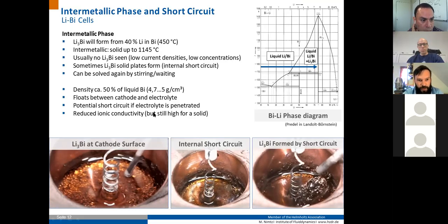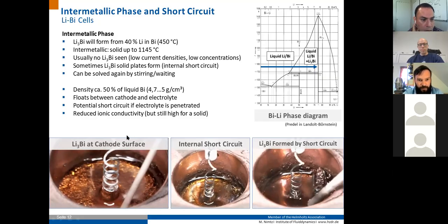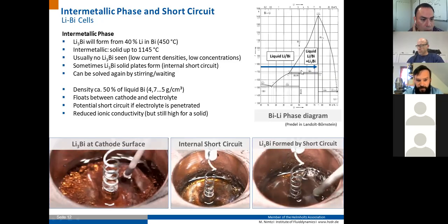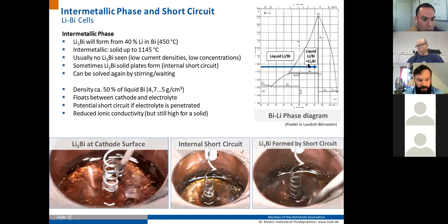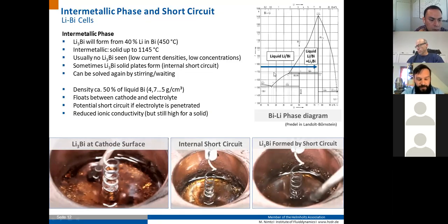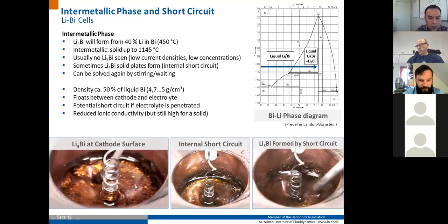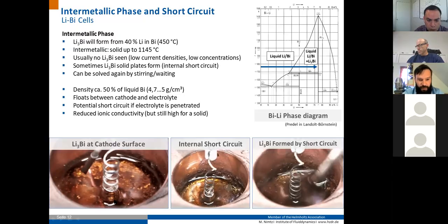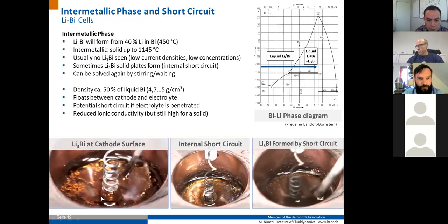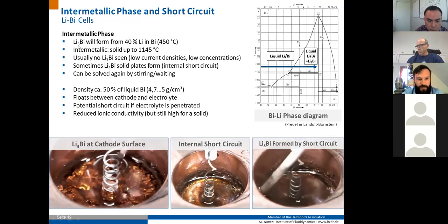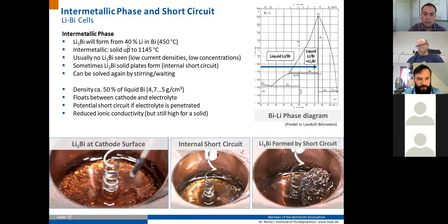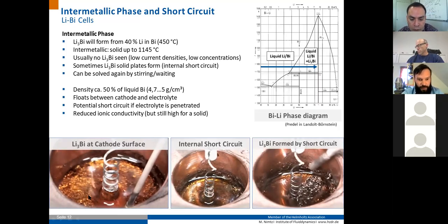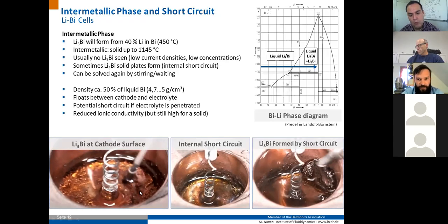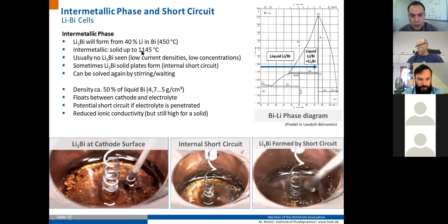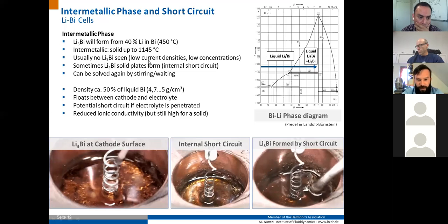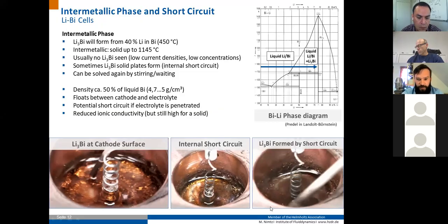This is something you usually try to avoid because the intermetallic phase, the two-phase region here, has a lower diffusion rate for lithium, which means the discharge behavior will not be as good as fully liquid metals. Typically, for a lithium bismuth cell, the intermetallic phase will form at 450 degrees Celsius from 40% lithium in the alloyed electrode. And this intermetallic phase, if it's solid, has a melting temperature of 1145 degrees Celsius. So it's quite hard to remove this solid intermetallic phase by melting.